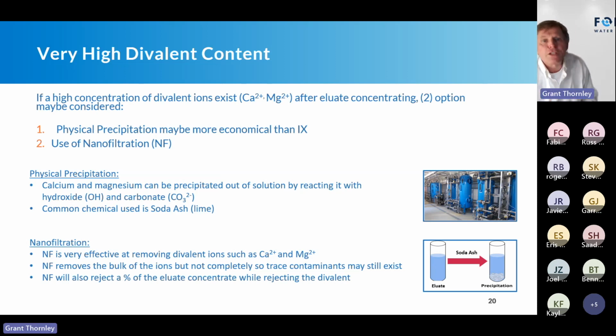So let's talk about physical precipitation. If I have calcium and magnesium, to physically precipitate that, I'm going to react it with, let's say, hydroxide and carbonate, like a soda ash. The reactants will create the products of calcium carbonate and magnesium hydroxide, and it's going to hit the solubilities and drop out of solution. So as part of that physical precipitation, I'm going to have a physical removal. It could be a filter, it could be a DAF unit, it could be an inclined lamella that has to physically remove those solids. Very common is soda ash or lime.